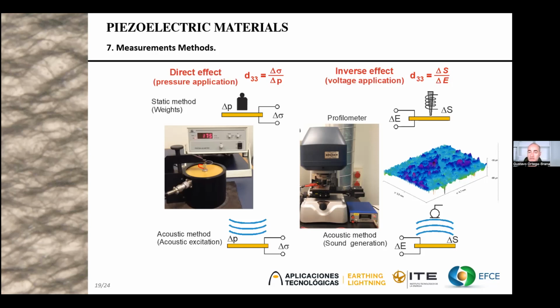One interesting method that we use to measure the displacement was a profilometer, the device on the right. The device can scan the surface of the sample and measure the displacement when an electric field is applied, and this device uses white light. Another way of measuring the d33 coefficient is using acoustic methods, introducing a pressure wave, or, on the other hand, applying an electric field to the sample and measuring the pressure wave that it produces.